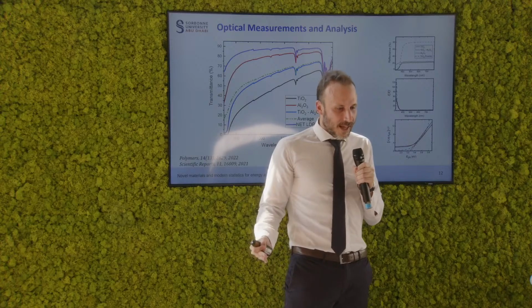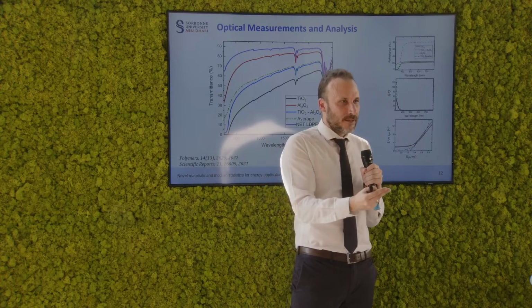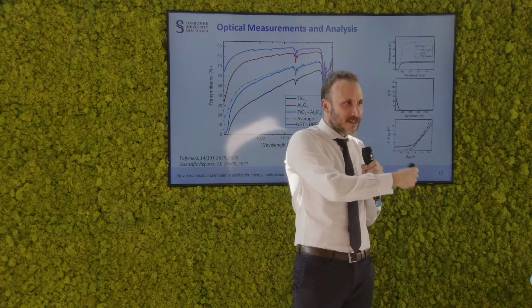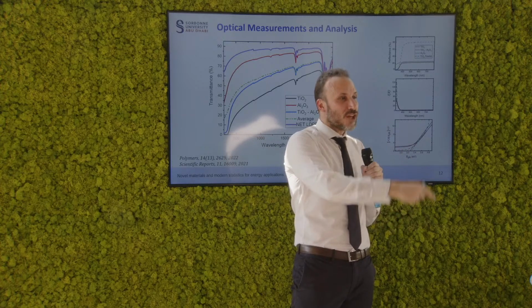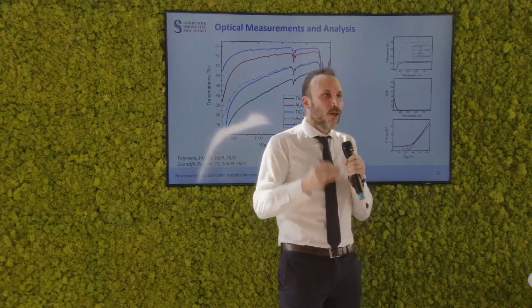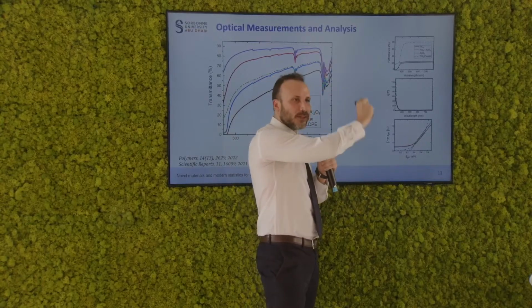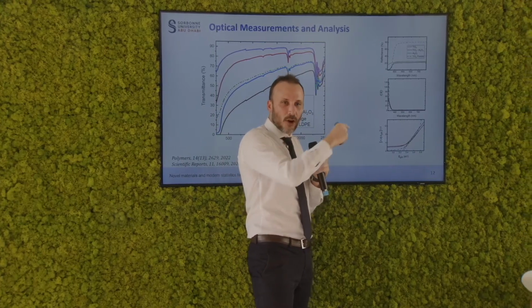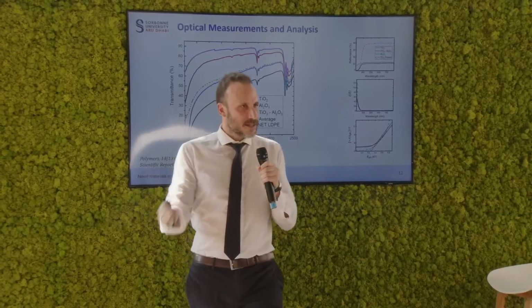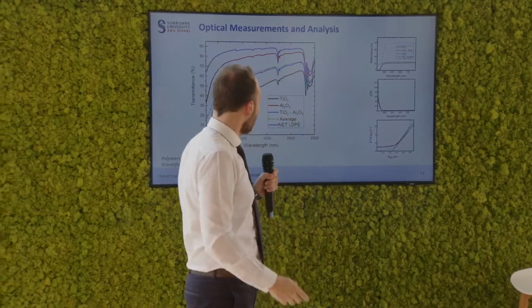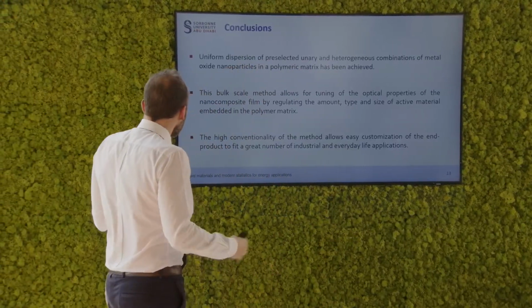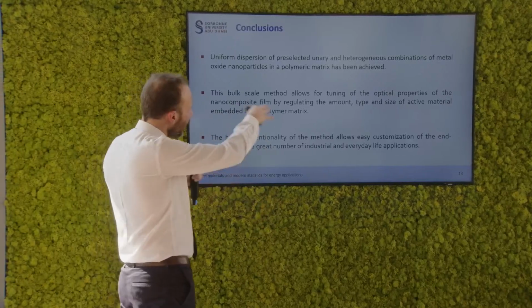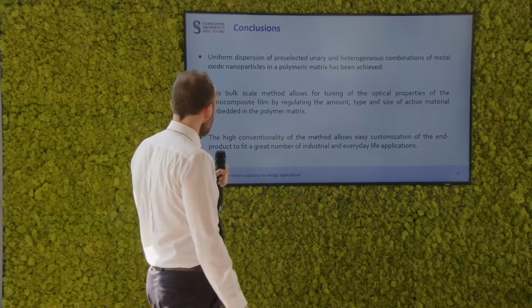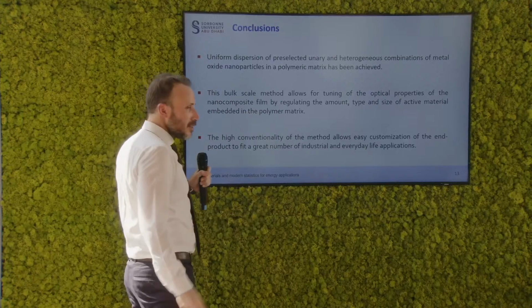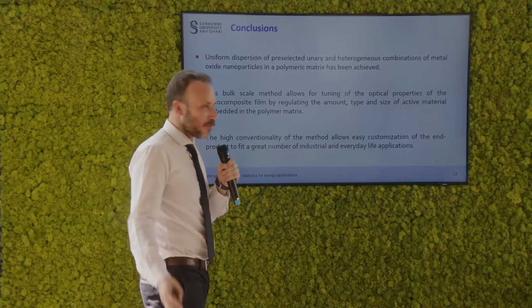The idea here is that when you have some properties in mind, the particle size is what defines them. So if that changed, so would the properties. But here, we can start selecting properties of particular nanoparticles, knowing that our process will not alter their size until the very end product. So we have achieved a uniform dispersion of preselected unary and heterogeneous combinations of metal oxide nanoparticles in a polymer matrix, and that's the proof of principle.